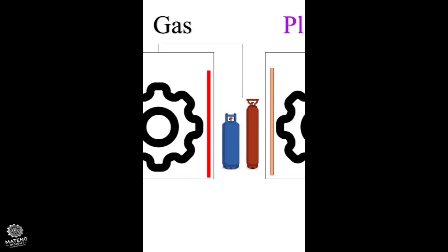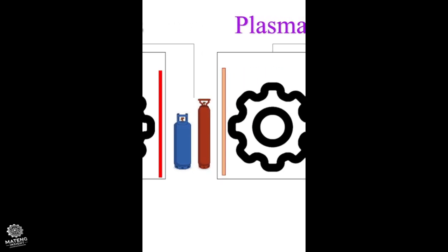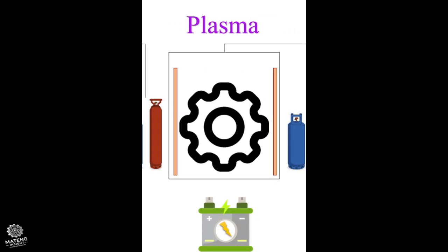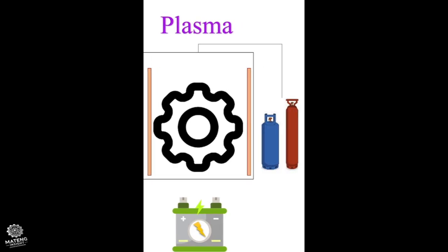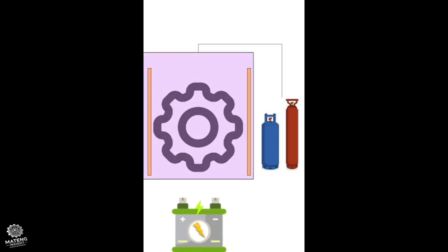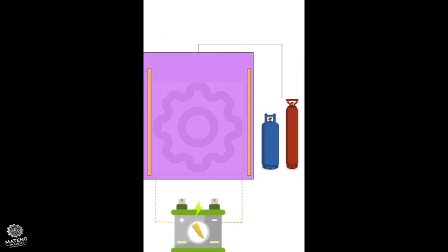Plasma nitriding. This process is similar to gas nitriding, but an electrical voltage is applied, ionizing the gas into plasma. Plasma not only supplies nitrogen but also provides part of the heat required. This process can be performed at lower temperature, so reducing distortion and dimensional change.